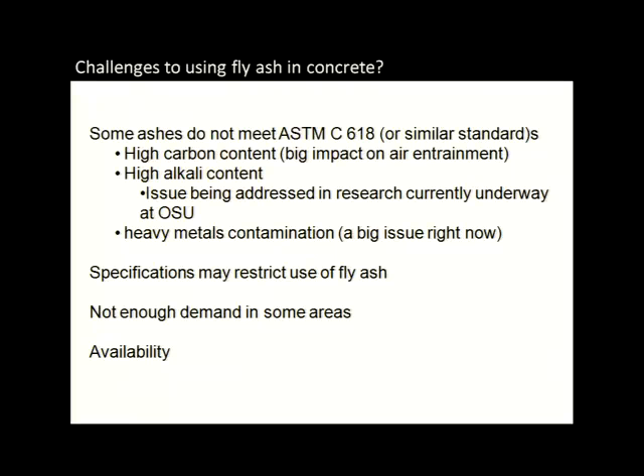There are some challenges to using fly ash. One of those is the alkali content of the fly ash itself. Even though you may be replacing a portion of the Portland cement, the alkali coming from the fly ash may exacerbate ASR concerns. We have a project with the Navy that's looking at better ways to characterize the fly ash to use it in concrete more effectively.